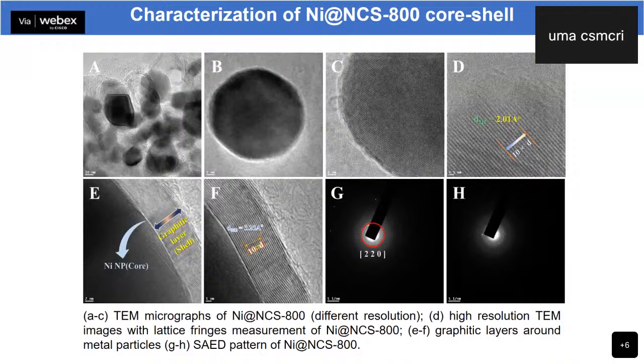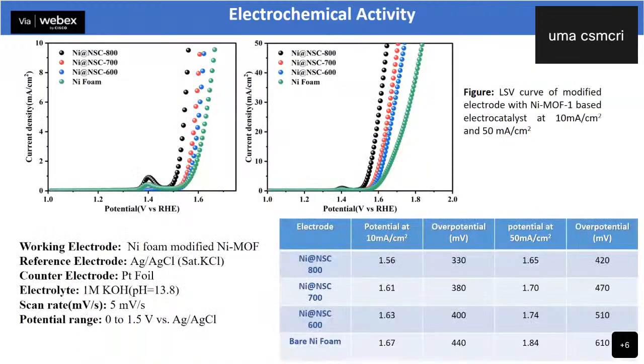Then TEM analysis, we performed the TEM analysis. We found that the nickel nanoparticles are well covered by the graphitic layers of carbon materials to provide the stability to the materials. After that, the material was used as an electrode material.